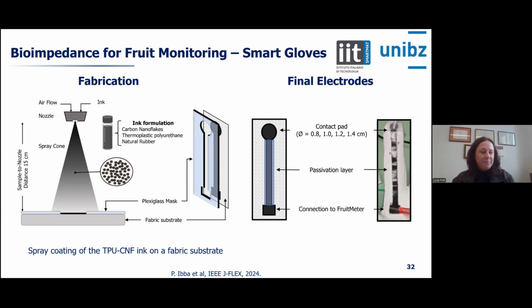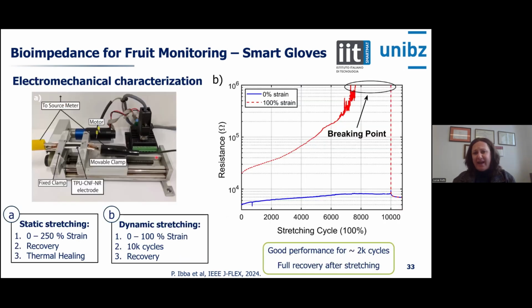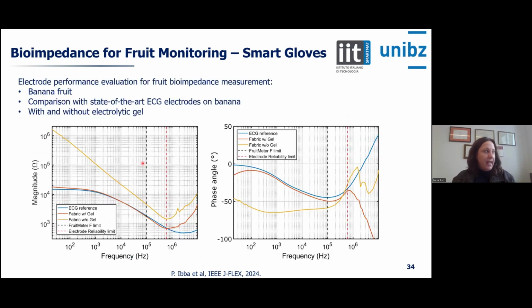And I think here is where we need a lot of work in the field, on the connection and the integration. We did a lot of electromechanical characterization, both static and dynamic. Of course, if it's a glove, it will have a lot of stretching application. You see here there is also the dynamic stretching up to the breaking point, but with good performance up to 2000 stretching cycles, and also full recovery. You don't see it from this picture here, but there is also full recovery after stretching with our custom-made bending, twisting, stretching machine.